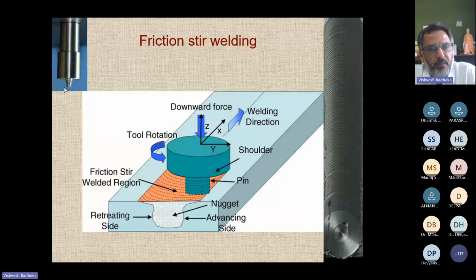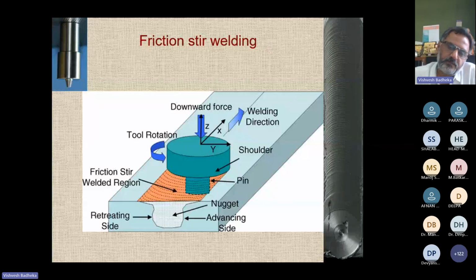The main heart of friction stir welding lies with the tool. The friction stir welding tool is a non-consumable tool, and there are two major elements: one is the pin and the other is the shoulder. The pin is mainly responsible for material flow, while the shoulder is responsible for generating the heat. The shoulder generates around 80% of the heat, while the pin generates around 20%, because the pin's main function is to mix the material at the interface.